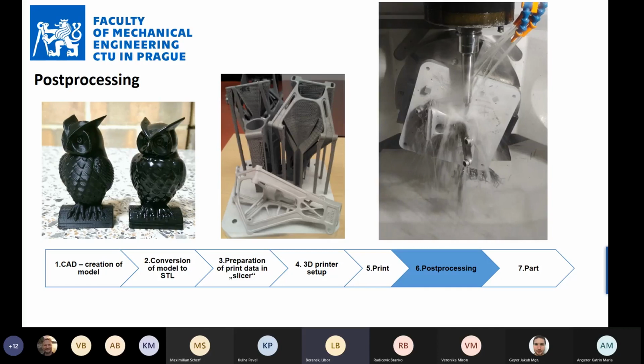So the part's deformation is much bigger than the final tolerances of the part, and you have to be able to do something with it. So one way to face the deformation is that you can pre-deform the data you are printing, and you can basically start with the simulation and pre-deform it a little bit. Still, this is the way to get, for example, from 2 millimeters to 1 millimeter or 0.8 millimeter.